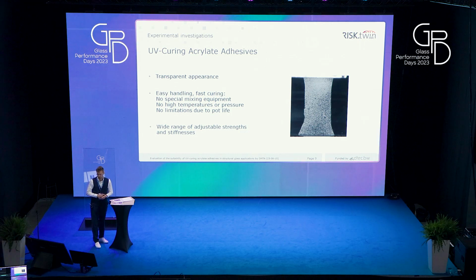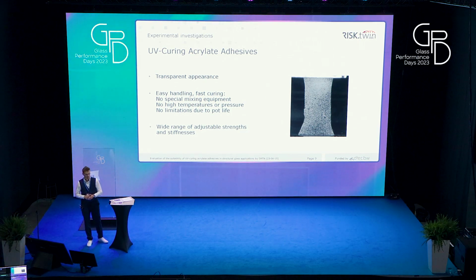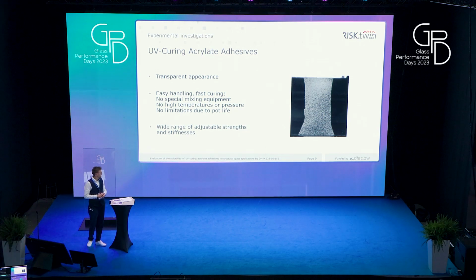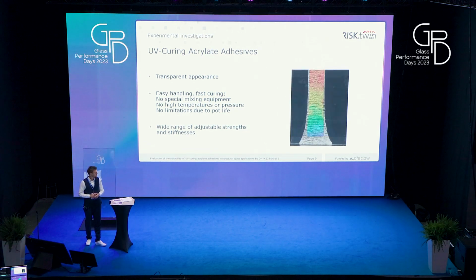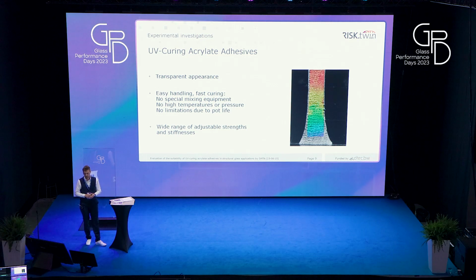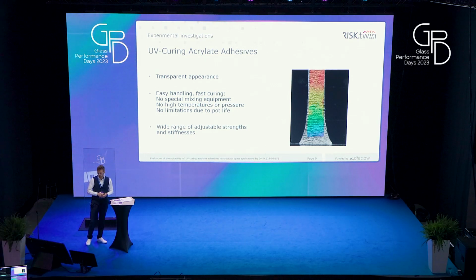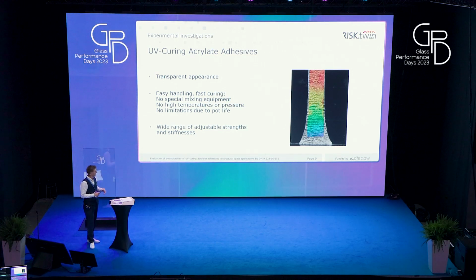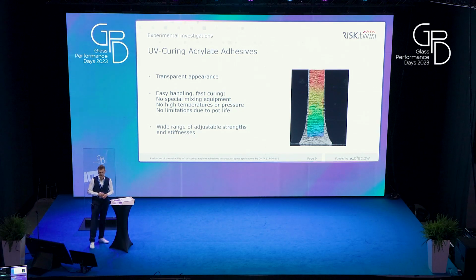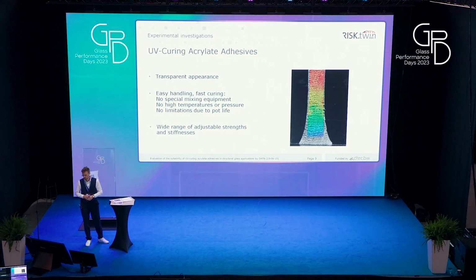And additionally, they allow a wide range of strengths and stiffnesses to be adjusted. To demonstrate this, we can have a look at some uniaxial tension tests which we performed. And as we can see, we can get quite long elongations using acrylate adhesives. And here the adhesive is of course not transparent, because we sprayed it with a speckle pattern for the digital image correlation, which we use to measure the strains.